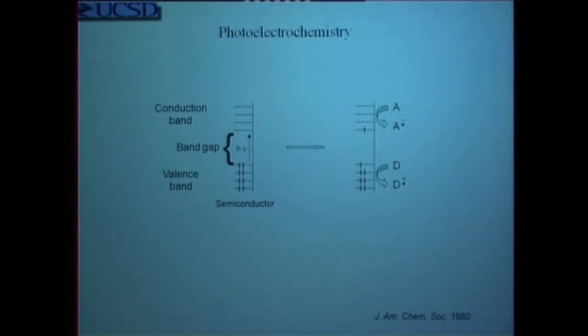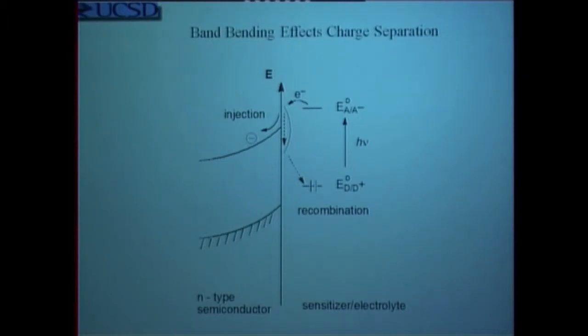Now, one thing that helps a lot to get reactivity in a titanium dioxide surface is that there's bending of the bands. What this does is that when an electron is ejected into the titanium dioxide, it moves away from the surface, and as a result, anything that's adsorbed on that metal or solid surface has a chance to undergo reactivity rather than simply recombining with the higher-lying energetic orbital. That recombination wastes energy, and it's one reason why the efficiency of this water splitting done in this indirect way is not as efficient as a process which would use photons directly. It does, however, harvest light.